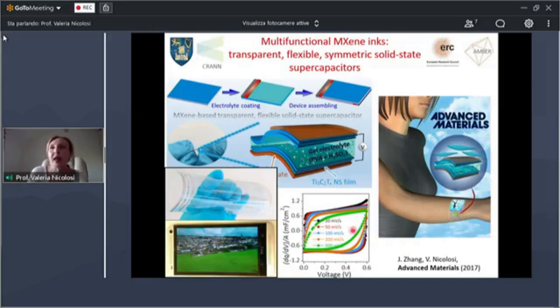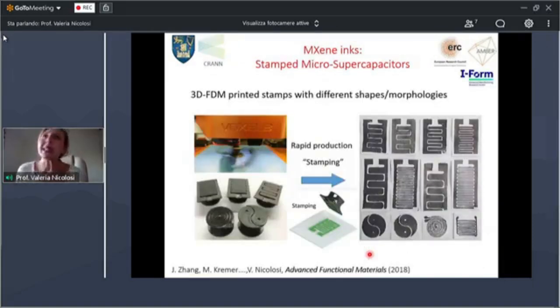And indeed, we show that they really perform well as supercaps. You can indeed store energy, and they're also very good in terms of rate performance. You can push them up to 500 millivolts per second to actually start getting some sort of resistive behavior. So very high rate charging and discharging performance. More recently, because we have such beautiful inks, they're very, very processable. So we thought, we need to develop something that allows us to test these inks very fast, that allows us to prototype things very fast.